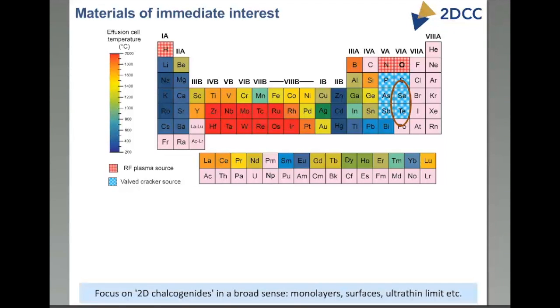Well, if you look at this table here, the selenides and tellurides and sulfides are certainly some of the materials that we are interested in generically. And there's the bismuth and antimony selenides and tellurides that we will be growing here at Penn State. We already have an existing MBE chamber, and these are the so-called topological insulators. They can be three-dimensional in their crystal structure. So in other words, you can have a thick film, but the two-dimensional aspect is really at the surface.